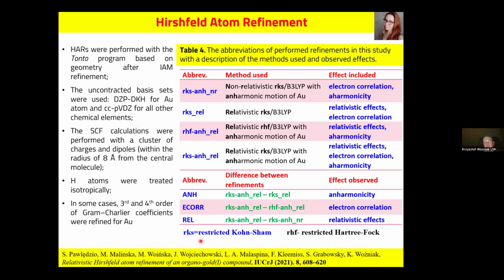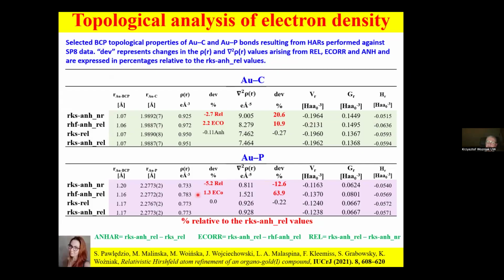levels of theory, using restricted Kohn-Sham approach, using restricted Hartree-Fock approach, using relativistic basis sets and non-relativistic ones, applying anharmonic motion correction, accounting for anharmonic motion of the gold atom, and treating the gold atom in harmonic approximation. So by taking differences in electron densities obtained at these different approaches, we can get information about consequences in electron density of anharmonicity, of electron correlation, and relativistic effects. And never mind numerical values, we can quantify them.